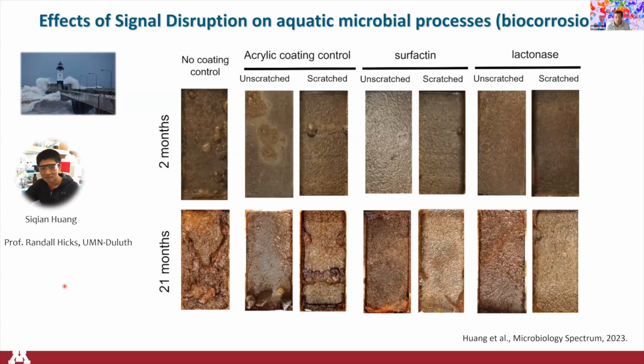These coatings with these enzymes were tested also in the field, and this was work that was done with Sichuan. This is an experiment, for example, that was conducted in the Duluth Superior Harbor, this time in acrylic coating. And here you can review some of those sample coupons. This was recently published a few months ago. So you have the no coating control that shows a lot of biocorrosion after 21 months of submersion in the harbor, lots of biocorrosion and lots of fouling.